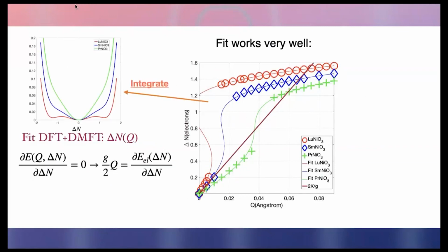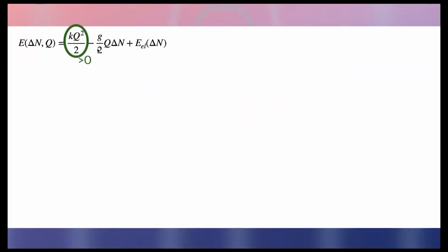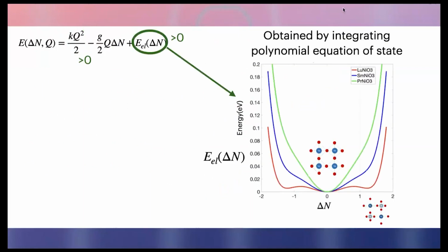And as a result, you actually get these energies. So you get three things. One, K is always positive. So maybe unsurprisingly, the lattice tends to not want to be disproportionated if you don't include these d orbitals. Interestingly, the electronic part also opposes disproportionation.